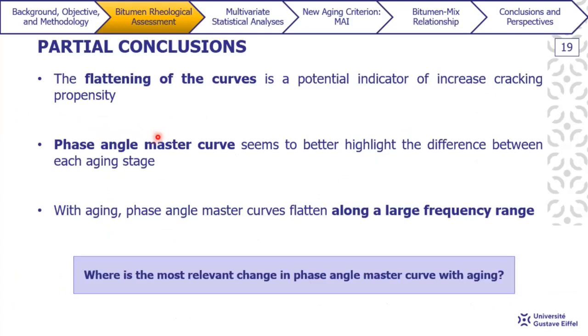So now here are some takeaways of this part, the bitumen rheological assessment. The flattening of the curves indicates an increasingly elastic and less viscous material with reduced relaxation ability, which is often a potential indicator of increased cracking propensity. From a graphical point of view, the phase angle master curves are farther apart from each other when compared to the complex modulus master curve, so this seems to better highlight the difference between each aging level. And with aging, we could also observe that the phase angle master curve flattens.